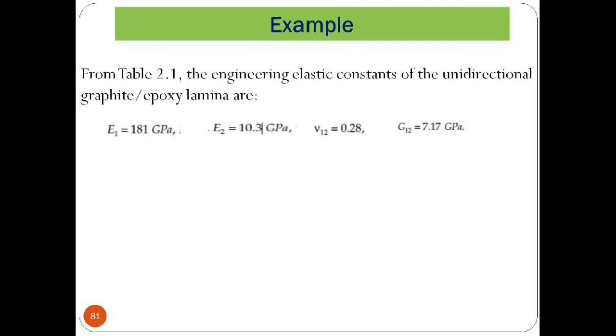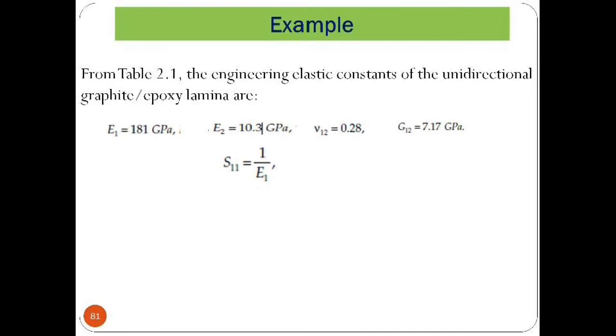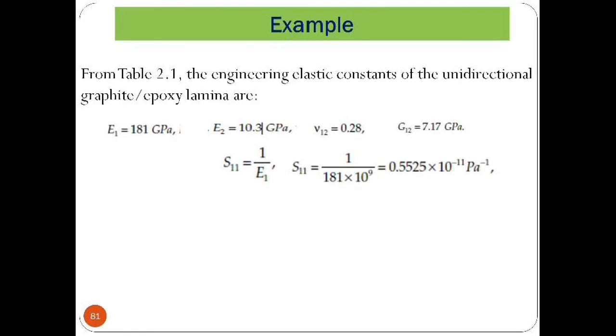Similarly, the in-plane shear modulus, in-plane meaning the 1-2 plane, G12 equals 7.17 GPa. Now, if you remember the discussion from module 2, which I used as a prerequisite for this module 3, S11 equals 1 over E1. So this would be calculated as S11 equals 0.5525.